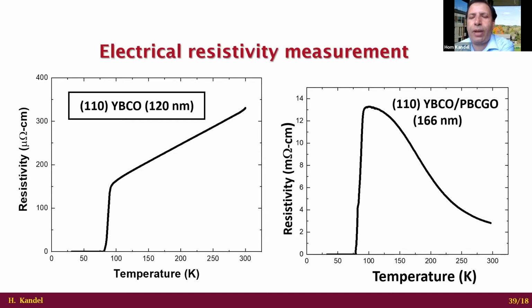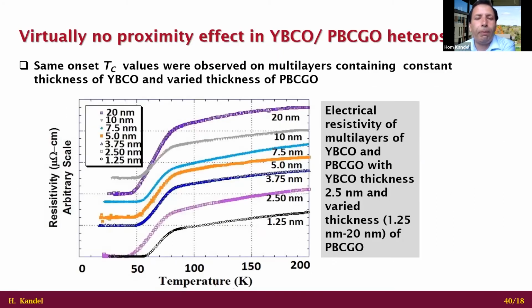On top of that base layer, 110 YBCO, and its TC0 value is almost 82 Kelvin. And likewise, next slide, please. We performed thin film growth and electrical transport measurement of this heterostructure containing YBCO with a 2.5 nanometer thickness, and then we varied the thickness of the top layer of 110 PBCGO from 1.25 nanometer here to 20 nanometer.